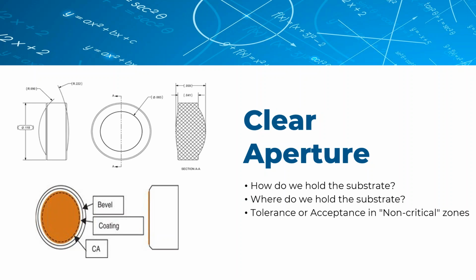The other thing about clear aperture too, and again, we're getting back to subjectivity here: if an adhesion loss or a coating flaw is outside of the clear aperture, is that still acceptable? We believe it to be. If it's outside of the clear aperture, which has been specified as the critical zone, then technically it should not count as a failure if you have poor adhesion and the adhesion loss doesn't run into the critical zone, and the coating flaw, be it a pinhole or something else, is not in the critical zone. So outside of the clear aperture, really any flaw should be acceptable and any holder mark should be acceptable. But again, this would be subjectivity, and this would be something that you would need to discuss with a coating supplier so you're all on the same page as you move forward with the program.